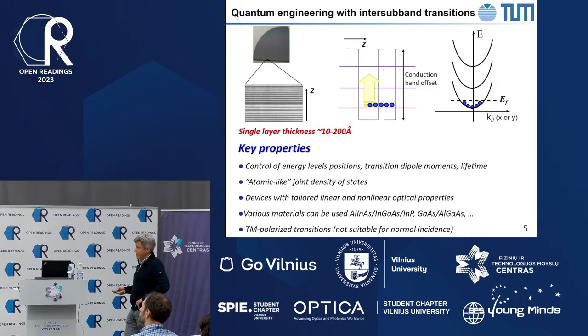These transitions are all polarized in the z direction, as you may imagine, because the layers are going in the z direction, which means that the electric field has to be normal to the surface of your structure, which makes it a bit difficult to couple light at, let's say, normal incidence, and we need to do some tricks.